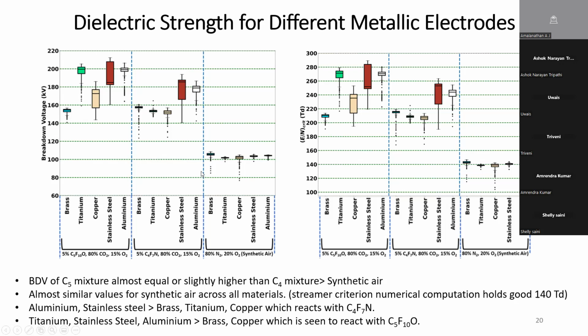For synthetic air, of course, in the literature a lot of work has been done. You see almost similar values for all materials, because synthetic air is inert, so it really doesn't react with the cathode materials. And also I did my streamer criteria numerical computation, and the computation came up to 140 Townsend, which is absolutely what we got from experimental results as well. So this is a good validation that our experimental setup is good.